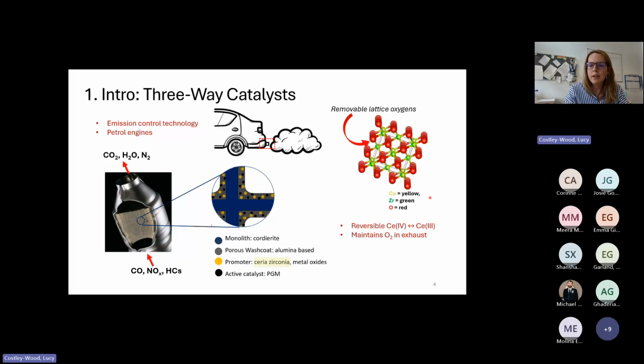These yellow and green spheres represent either a zirconium cation or a cerium cation, and the oxygens are red. You can remove up to 25% of oxygens from a 50-50 ceria zirconia structure, and this happens concurrently with the reduction of cerium 4 to cerium 3. This oxygen removal is so crucial because when your exhaust is running in low oxygen concentration environments, it can provide additional oxygen to make sure that all of the CO and the hydrocarbons can be oxidized. Similarly, for the NOx reduction, if there's too much oxygen in the exhaust, it can take in some of the oxygen. This really widens the operational window at which these three-way catalysts can operate.